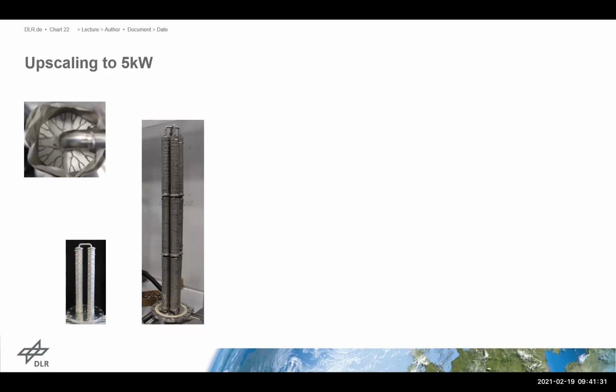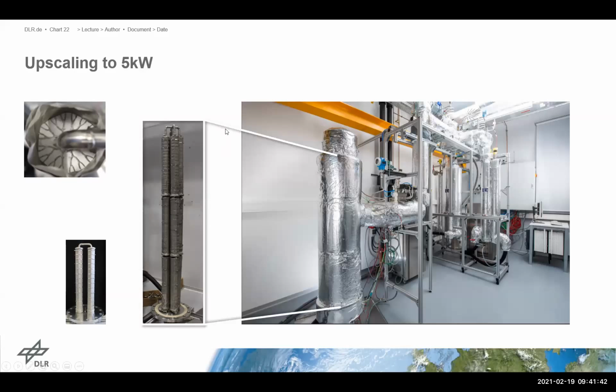This is now the last result. Basically, in the beginning of last year, we started with the experiments. There, 4 tubes, 3 times longer tubes. We have connected it to the test rig I explained before, and it works perfectly. The publication is now in preparation, but it's not directly scalable because the heat transfer fluid was not really able to transfer like 5 kilowatt of thermal power and maintain constant temperatures. So we have to work on that.